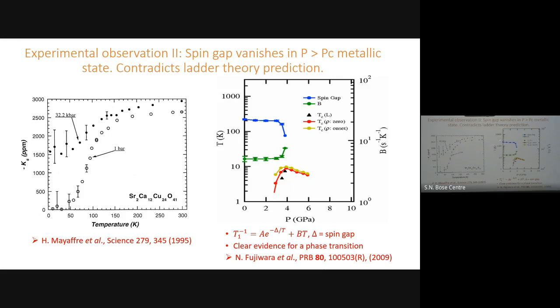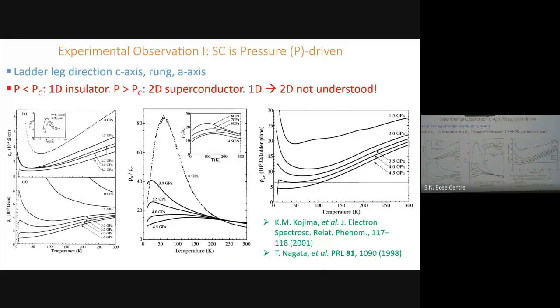let me skip this one. They are looking at the spin gap as a function of pressure. It is almost constant, but something drastic happens. And that's exactly where the superconductivity appears and reaches maximum. This is a phase transition, which may be related to this.